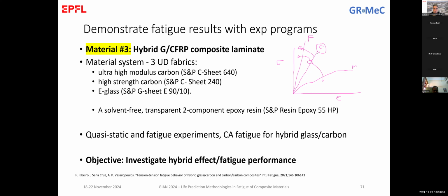This is because of the hybridization of the properties of the materials that are used for the mixing. In this case, what is the parameter for the hybridization? What is the difference in these materials is that the glass fibers, although they are less stiff and strong than carbon, assume more strain up to failure. So they introduce ductility to a very stiff system. And this is the reason that this combination of glass and carbon fibers gives a lot of benefits to a pure carbon composite material.